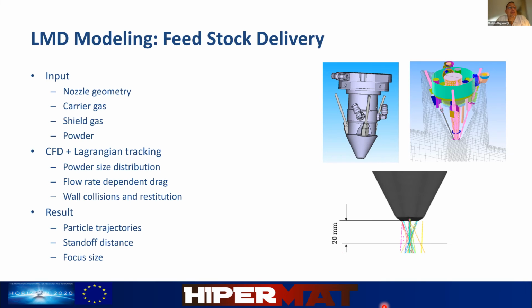The result of these simulations is the particle trajectories. We can extract the standoff distance or the working distance between nozzle and base plate, as shown on the right-hand side. For these flow conditions, we achieved a minimum focal diameter at about 20 millimeters away from the nozzle mouth. And we can also identify the focal size.